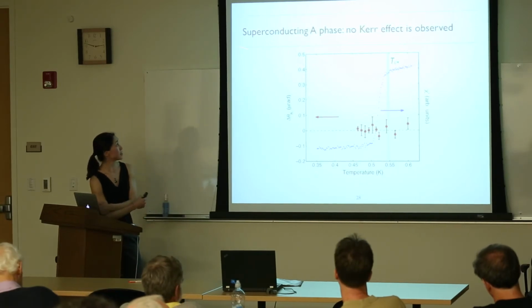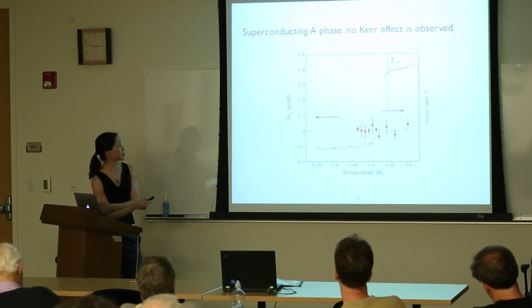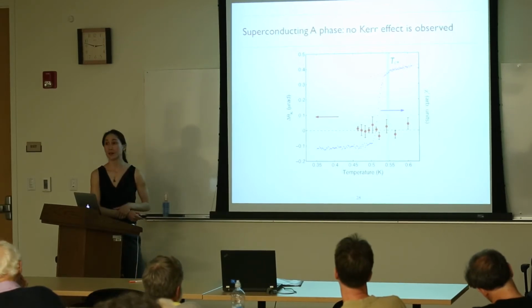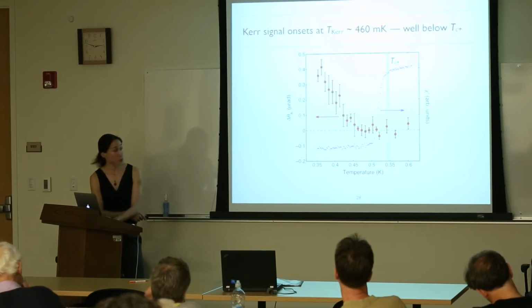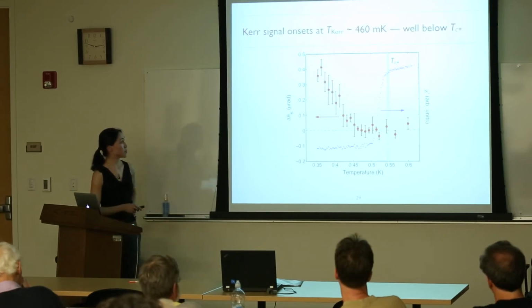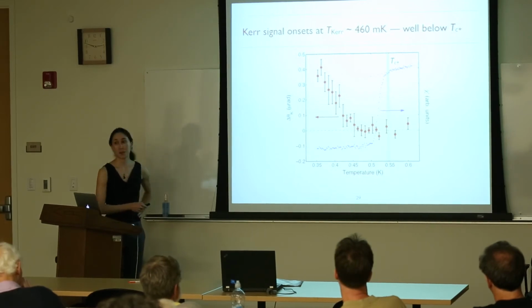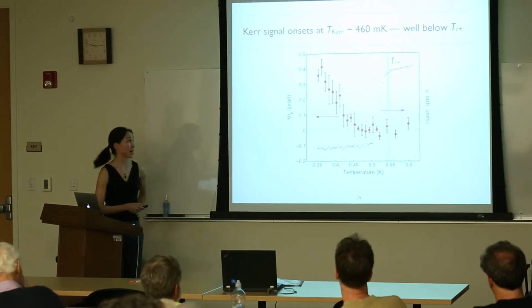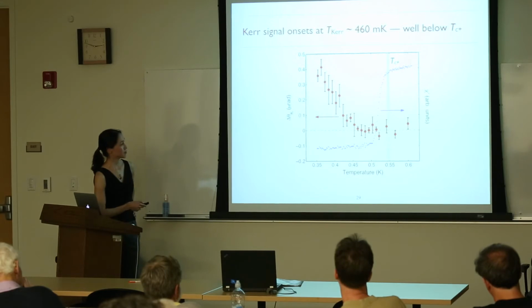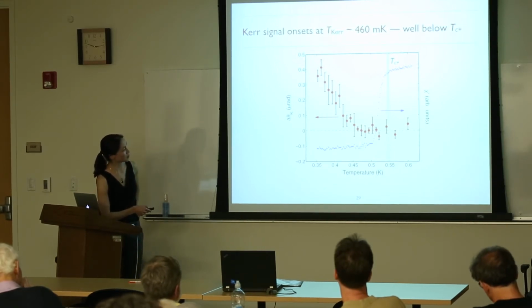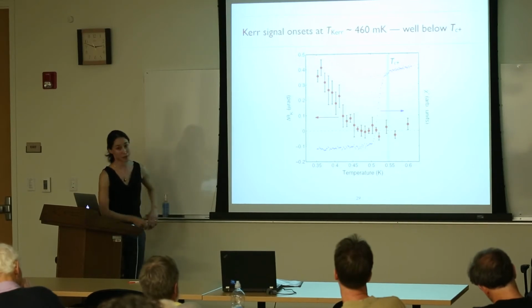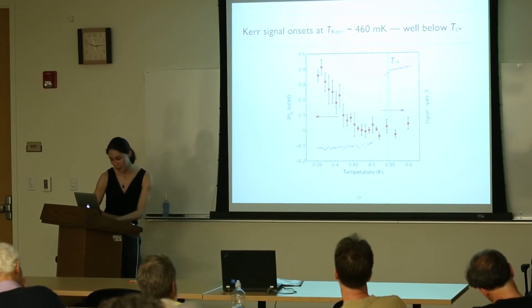And compared to that, at any rate, in the superconducting A phase, if we look at just the Kerr effect data, there again isn't a whole lot going on. So we're not able to see anything so far. But what's really striking is that as you go to still lower temperatures, now you get a pretty clear departure from the background of the Kerr angle. So that seems to be maybe around 450, something like that. It's hard to tell based on the size of the error bars here.